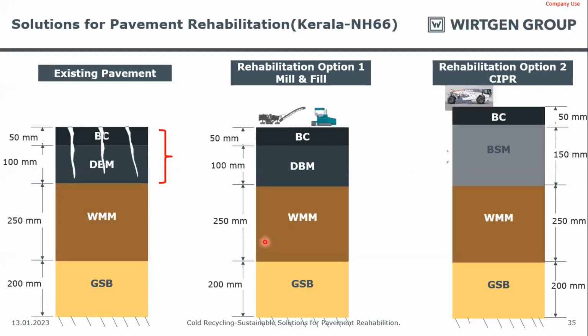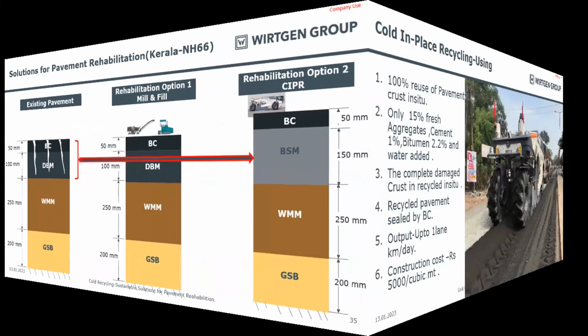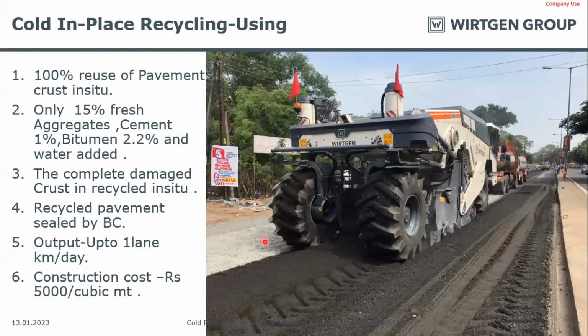Again, you have two options, either to go for mill and fill or BSM. So here we recycled the top 150 mm damaged asphalt layer and sealed it off with a 50 mm BC layer on the top. This project involved addition of 15% fresh aggregates into the system, 1% cement as filler, and the bitumen requirement was 2.2%. The complete damaged layer was recycled in situ, and then we sealed it with a BC layer on the top.